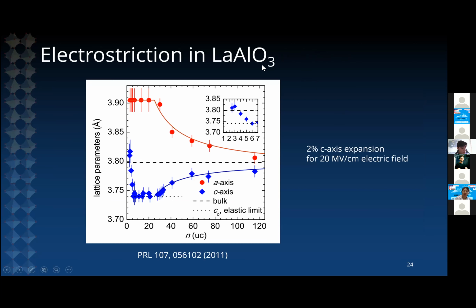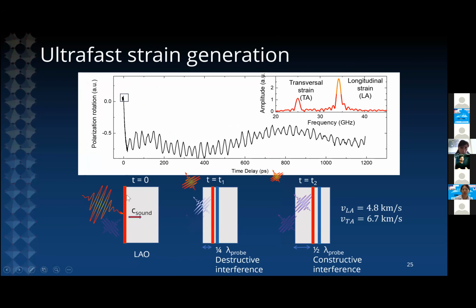The activation of the Raman mode is not the only phenomenon that we observe when we excite the crystal lattice. There is a second very important thing that occurs, which is due to electrostriction in lanthanum aluminate. So electrostriction is an expansion of the lattice parameter of an insulating material in response to the application of a static electric field. And in the case of lanthanum aluminate, if you apply an electric field of the order of 20 megavolt per centimeter to a very thin crystal of lanthanum aluminate, you observe something of the order of a 2% expansion of the C-axis. So when the material is under the strong electric fields, there is an expansion of its lattice parameter, and this generates a strain wave in the system.